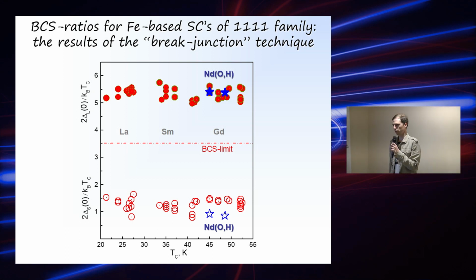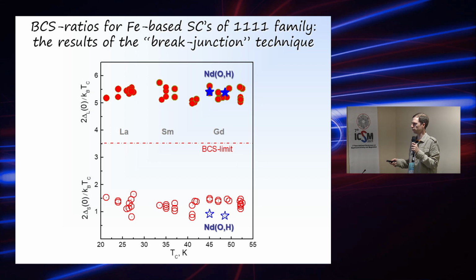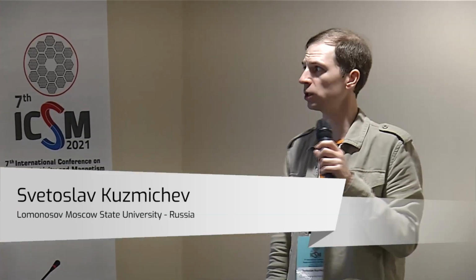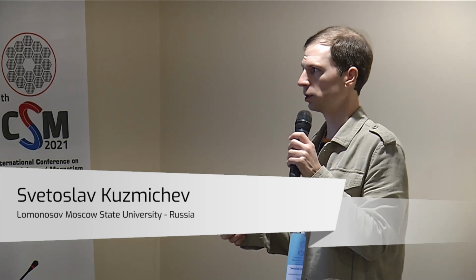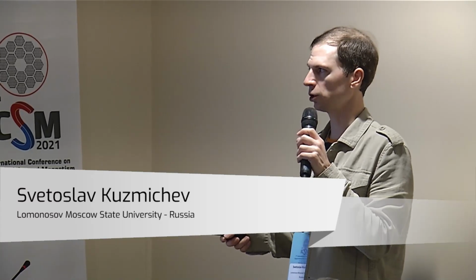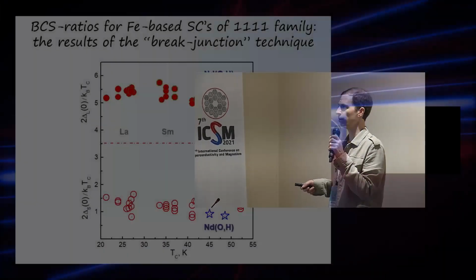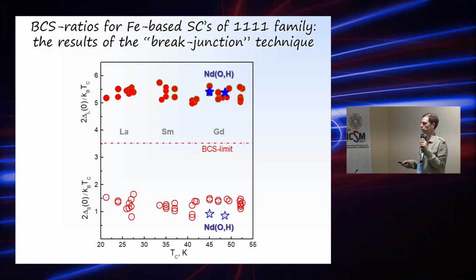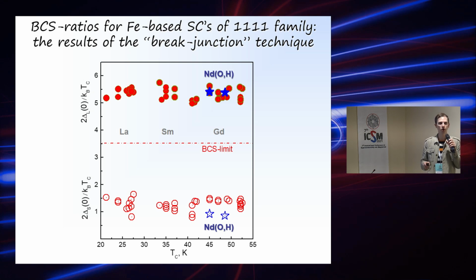Thank you. I could say that the size of the junction influences only the normal resistance, and we normalize our conductivity spectra to its normal value, I mean, above Tc. So it should not have any influence, but this characteristic ratio is something like the first derivative of the function of the superconducting gap amplitude versus critical temperature. Mathematically it is the same as the first derivative, and of course when you take the first derivative of some experimental data, you every time get large noise, but here the noise is not very large.